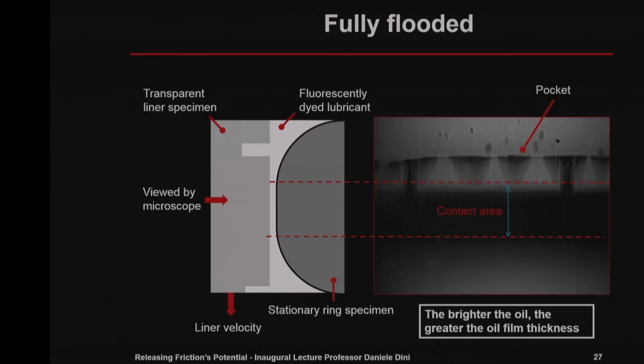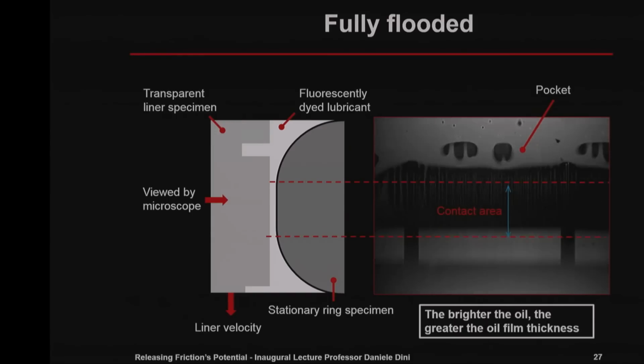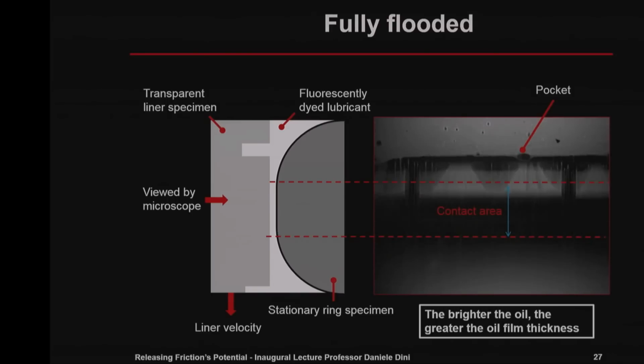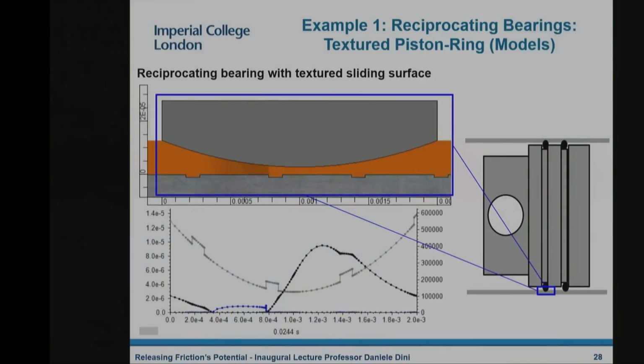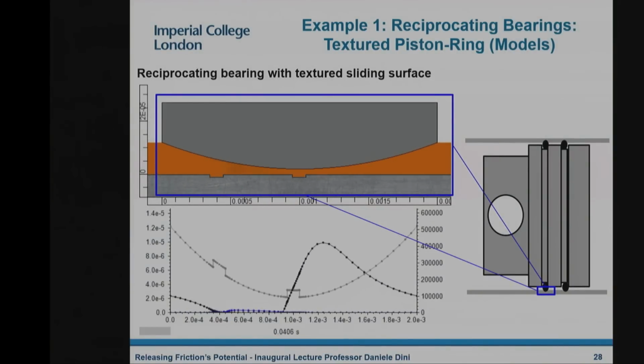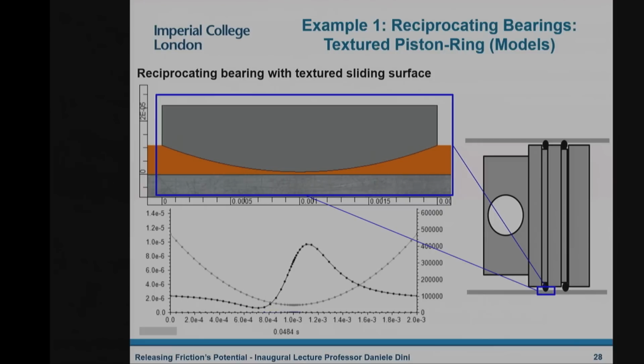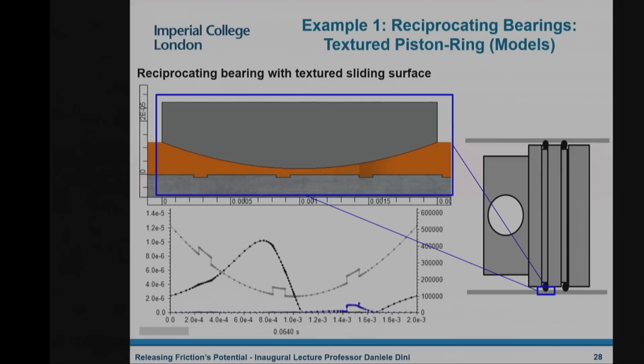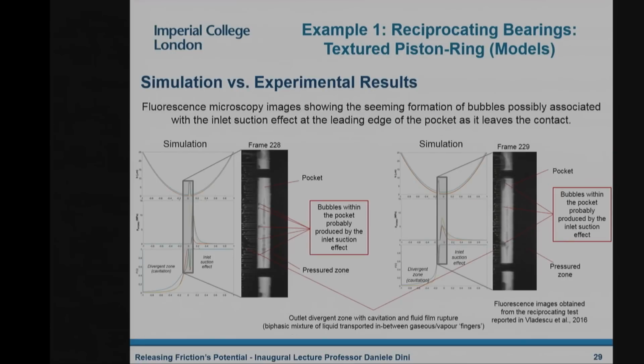And in fact, you can see pockets of bubbles forming at the inlet and the outlet of this system. And these obviously change as the velocity changes. And we have since managed to explain this by looking at models that explain exactly what happens when a pocket traverses a contact, where you see that there is a change in the fluid, there's cavitation happening in the fluid. The fluid is changing phase. And as a result of changing phase, there is a change in the way the system takes on pressure from the lubricant. And this is obviously very important because it explains what happens through these pockets and can be explained with models.